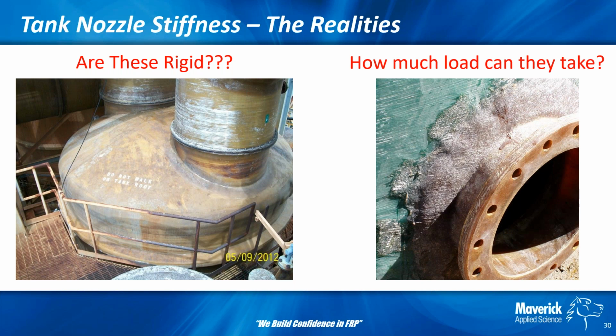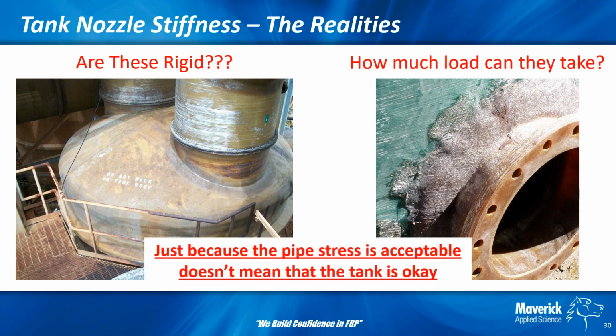Are these rigid? The left pick, you can't see it, but it actually says do not walk on. So if you can't walk on it, I would venture a guess to say it's not very stiff. Smaller loads can present problems with these nozzles. It doesn't need to be a high load to cause concern. Even that 300 foot-pound, 400 foot-pound could be a problem on these nozzles. Just because the pipe stress is acceptable does not mean that the tank is okay.